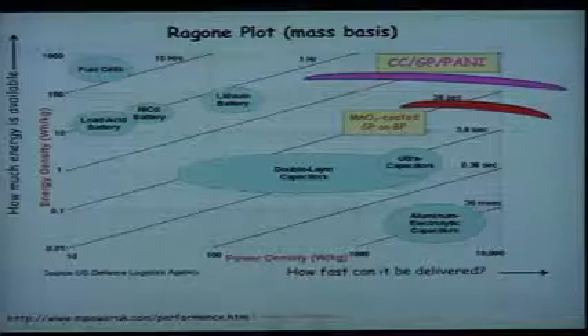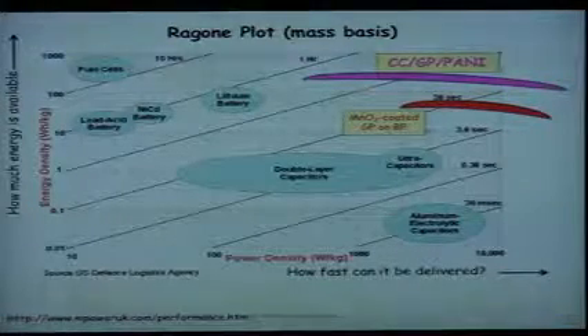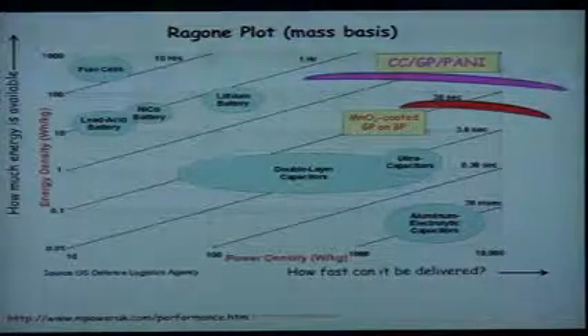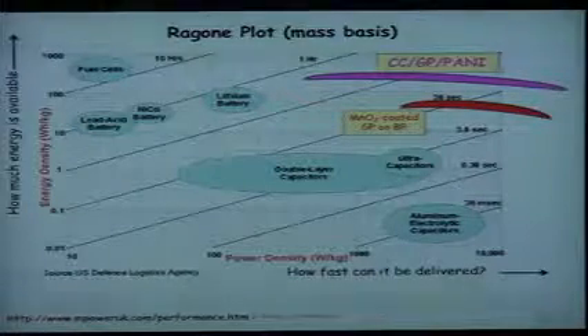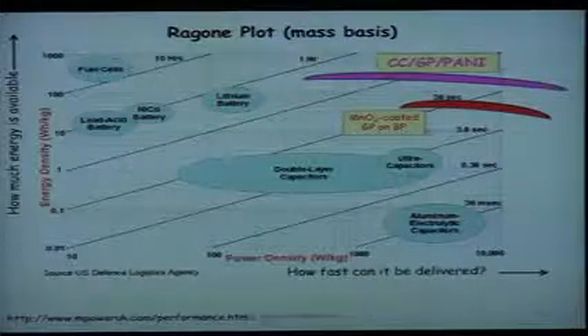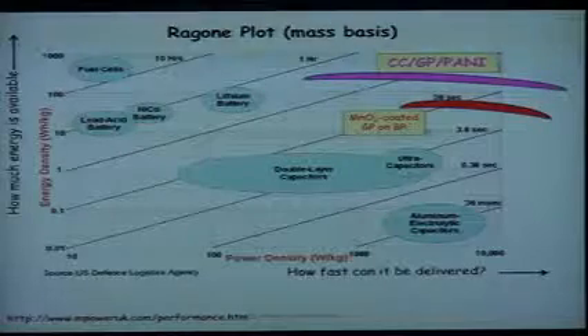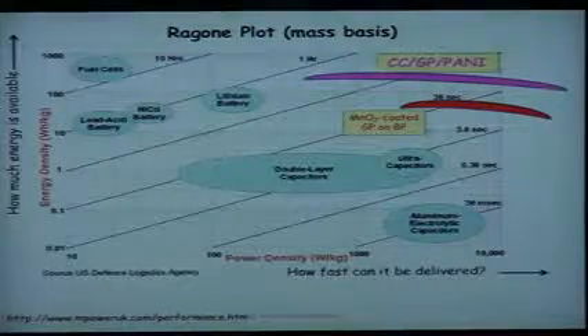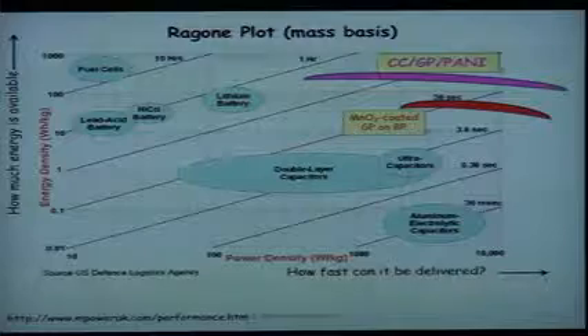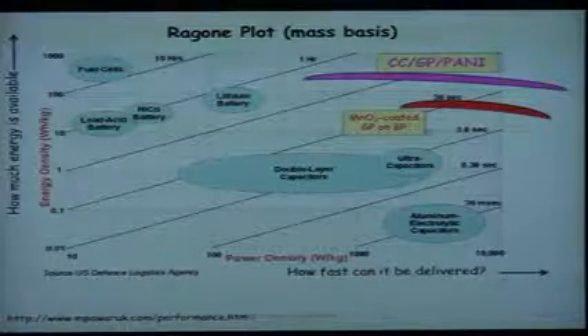And these are decades in time. And you see that this would be 6 minutes, and in the middle of that purple sweep, that would give you the energy density of a lithium-ion battery, but you'd be able to charge it in 6 minutes. Right? So technologically, that's important.